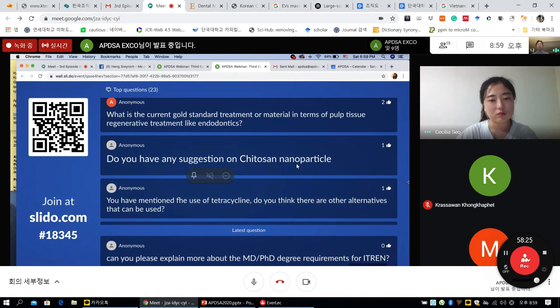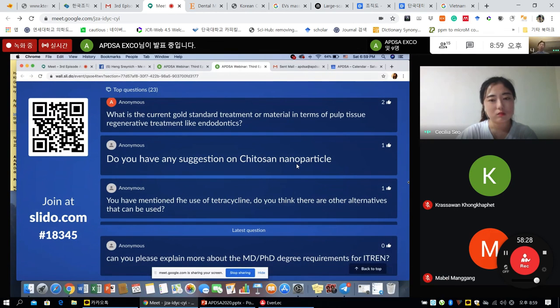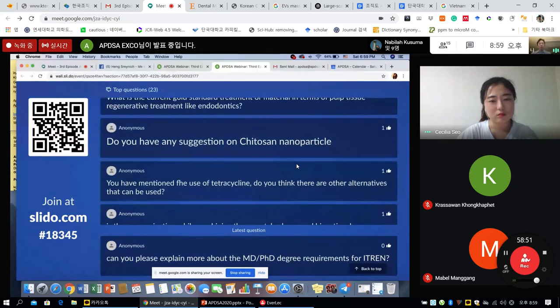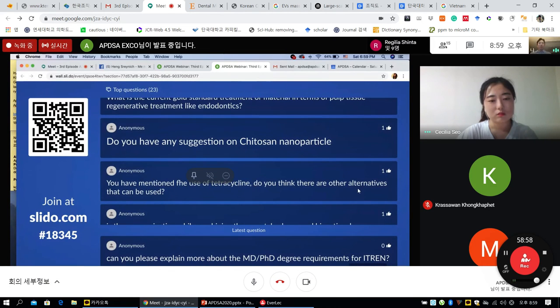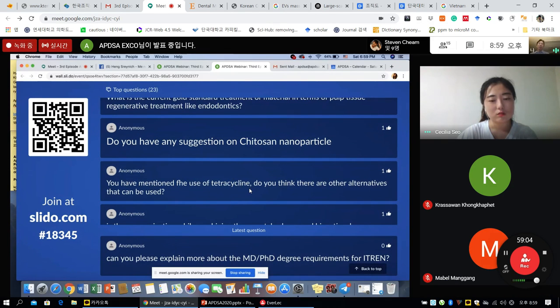Chitosan, yeah, chitosan has been used for maybe over 30 years. We can make chitosan nanoparticles, but they only dissolve in acid, near pH 5, which means it is sometimes a little bit toxic. And chitosan has very high viscosity, so it's not easy to apply. But when you can optimize it, maybe you can get good results. Without TC, we can use other antibiotics loaded in nanoparticles. Like I said before, TC was used as a model antibiotic because of its green fluorescence.